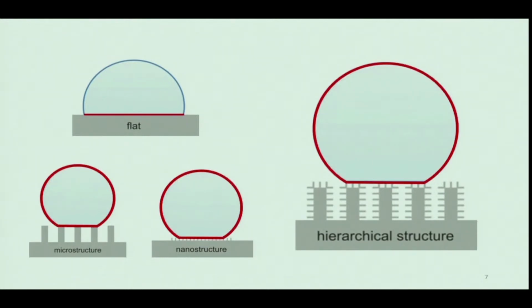And now if you take a close look into the shape of the water droplets for the case of only microstructures, only nanostructures, and hierarchical structures, they are actually the same, meaning that their contact angle values are the same. What's the difference then? What changes is the contact area. In the case of only microstructures, the contact area between the water droplet and the surfaces decreases when compared to a flat surface. But the water droplets still get stuck onto the surface.